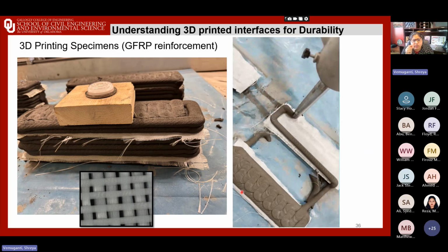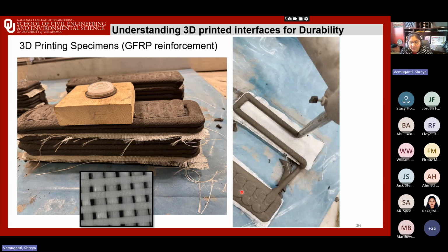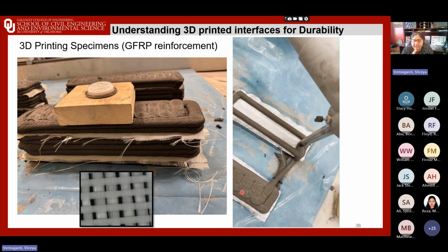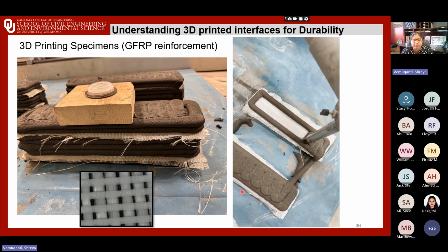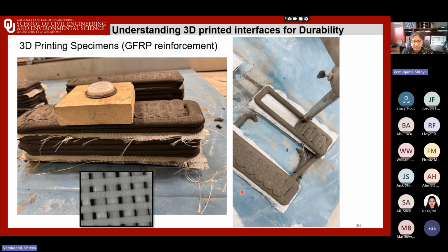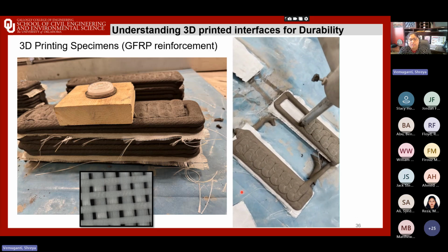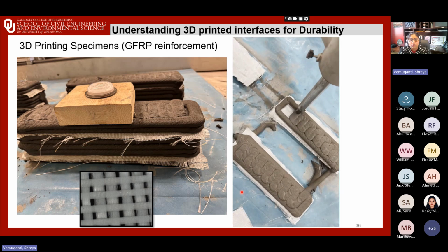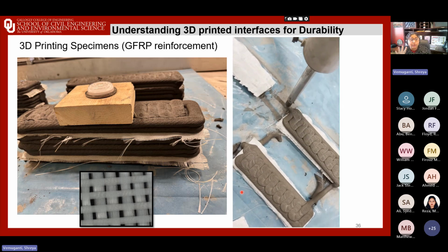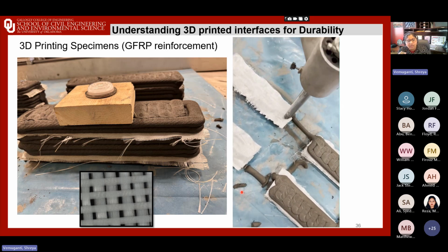If you look at these videos here, this is of our GFRP reinforcement. So essentially, this is a glass fiber reinforced polymer. And you see these fabrics laid on these specimens. We are doing 4 beams at a time. It's about a cubic foot of mix that we've calibrated and validated our mix design for. So every time we print, we ensure that these calibration parameters are stuck to.